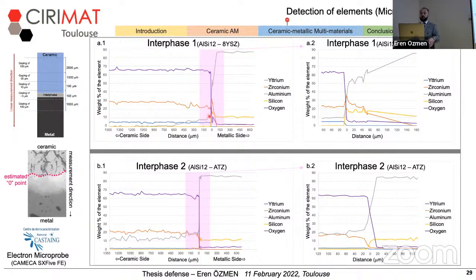So when we come back to large scale and check the detection of metallic aluminum, we see that up to 600 micron on the ceramic side, metallic aluminum can be detected. For the second interface, even though there is alumina and naturally aluminum inside this composition, we see that approximately up to 300 micron, the aluminum can be detected in the ceramic structure with a higher weight intensity.